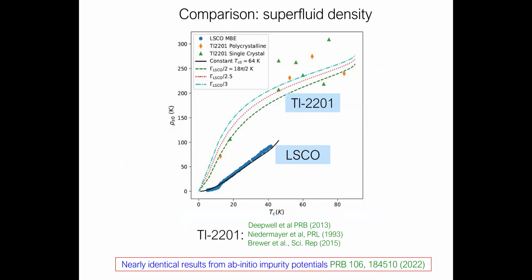Well, okay. I'll say a couple of things. In the sense of them being very different, I would say that the factor of 3 in the scattering rate you might consider to be very different, and it's clearly, within my hypothesis, eliminating the quantum oscillations in the LSCO case. That may be sufficient to do so. On the other hand, the theory is essentially the same structure. So in that sense, they're similar. I'd like to mention that people have, to my great delight, started working on the thallium 2201 system again. There was a hiatus of about 15, 20 years where nobody made a sample anymore. And they've found techniques to make much better samples now. And I think that's going to change the game when they get published.